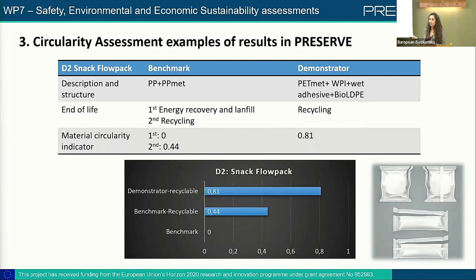So for this benchmark, the result will be, for the first hypothesis, 0, which means it's a totally linear product. And for the second, it will be 0.44. And for the demonstrator, you have here the structure. So we incorporate the BioLDPE and also the whey protein, and then the wet adhesive. And in this case, the end of life would be recycling, and this indicator was improved to 0.81. It's not totally circular, but we have a huge improvement in this indicator.